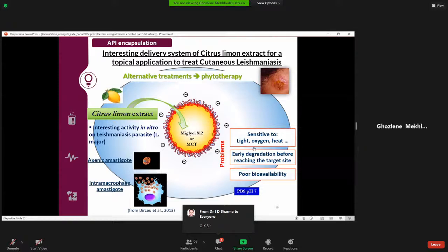So first, we evaluated the anti-leishmanial activity in vitro on L. major. It's a species of Leishmania causing cutaneous leishmaniasis in the north of Tunisia and in the south of France. We evaluated this activity on two different forms of the parasite cycle, the axenic form and the intramacrophagic form. An extract from Citrus limon is considered active against the L. major parasite, both on axenic form and on intramacrophagic form. And this good activity is comparable to that of miltefosine, the positive control.